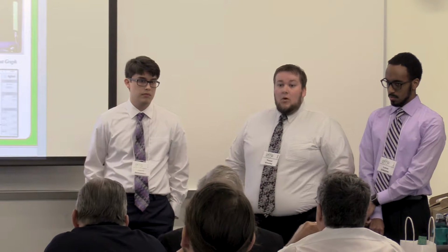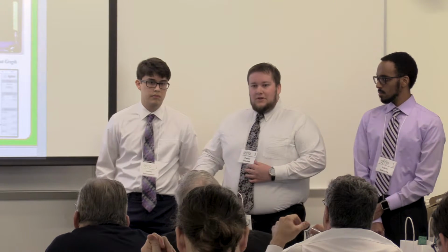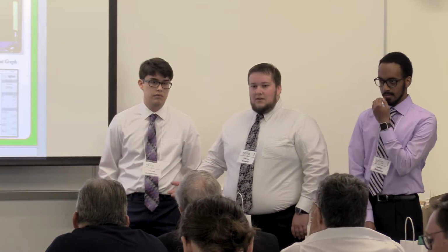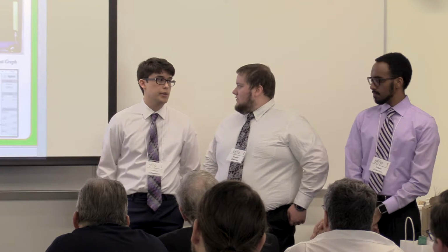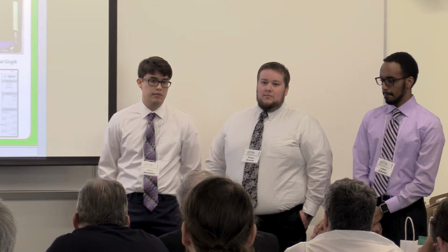What makes your FET gamma ray proof? Is that what you are trying to improve? Most particles, gamma, beta, or alpha particles, have all been tested to not affect gallium nitride on a massive scale. So whereas silicon can be affected by 1,000 rads, GaN can withstand millions of rads. And there is proven research by JPL and Berkeley Labs that backs this up, with equivalent GaN transistors to the ones we use. Radiation testing at the level that we need to do independently would take months, maybe almost a year, and it's extremely expensive. But the fact that we already have equivalent testing data on the exact same transistors proves it.